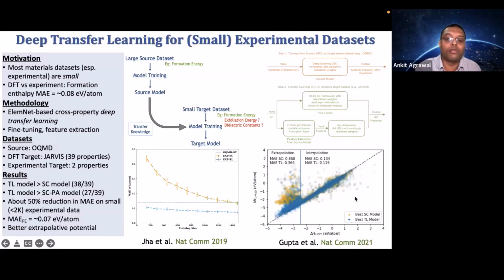We did some more analysis in terms of extrapolation. In a separate model training, we only gave this part: on the right of this blue line was given as a training data set, and then it was tested across the whole regime of these formation energy values. You can see in the interpolation regime, both the scratch and transfer learning models are doing reasonably well, although the transfer learning model is slightly better there also.